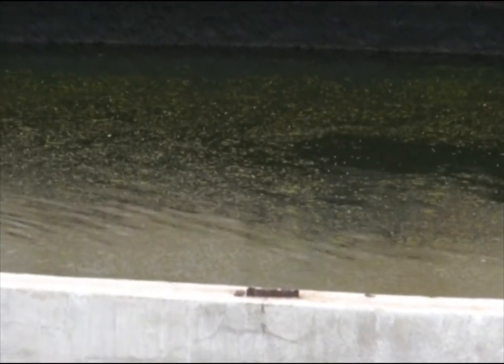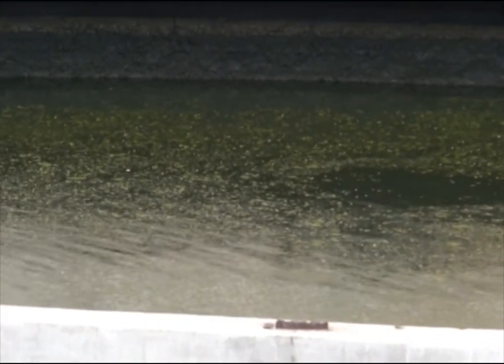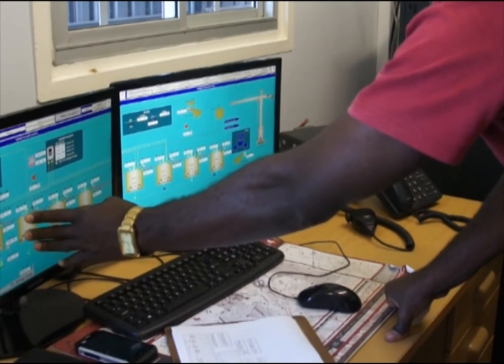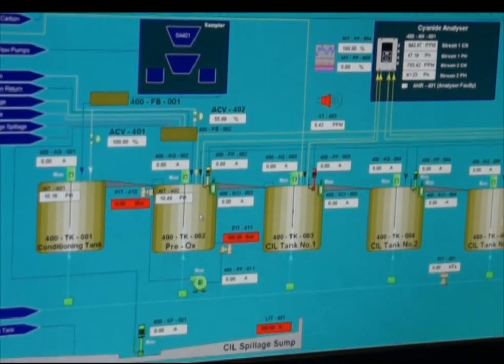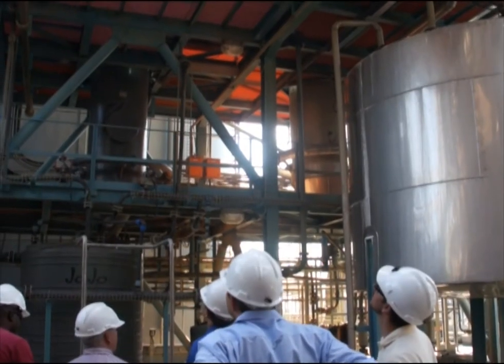The optimum conditions for the bacteria are about 40 degrees, a pH of about 1.2, and then you just add dissolved oxygen and nutrients to maintain the bacteria within optimum condition. At Pan African's Barberton Tailings Retreatment Project, technological innovation also helps add more gold each year at low cost to its mining output in Barberton.